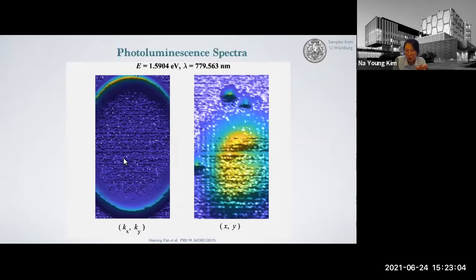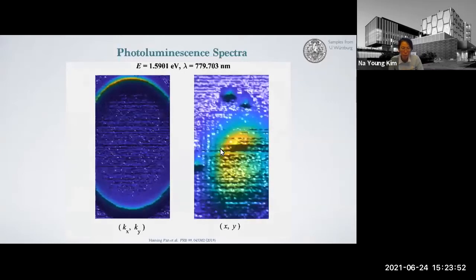On the left, I note there's a KX and KY. This is what we call the reciprocal lattice, or momentum space, if you're familiar with solid state physics. And on the right, what you are seeing is XY, the real space of the crystal structure, you can imagine. What I'm going to show in the movie is different slices of the energy. In other words, what you see is a kind of tomography of the energy band structure on the left, which closely resembles the ARPES band structure data I showed in the past. On the right is the real space exciton-polariton distribution, the intensity, which is analogous to scanning tunneling microscope images. Let's take a look at the movies.